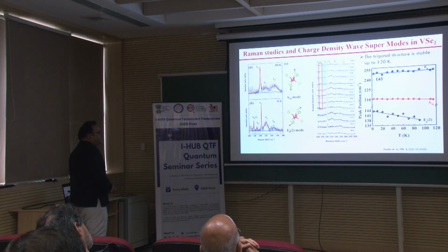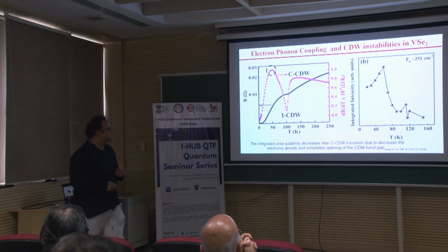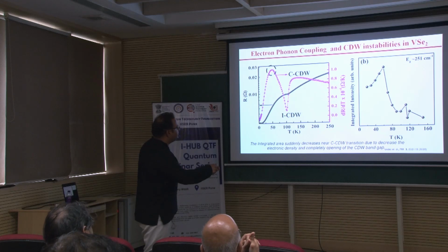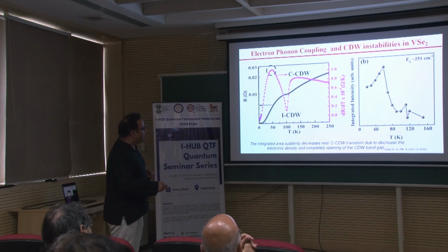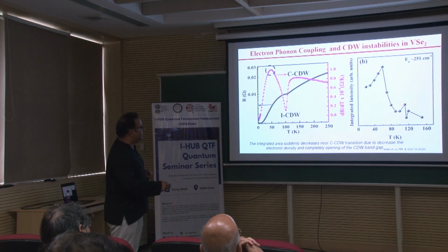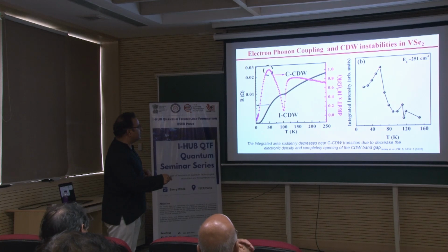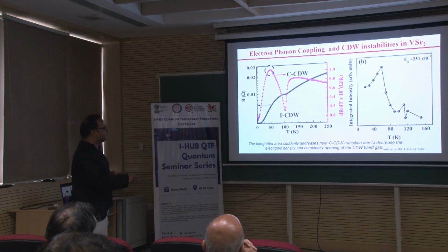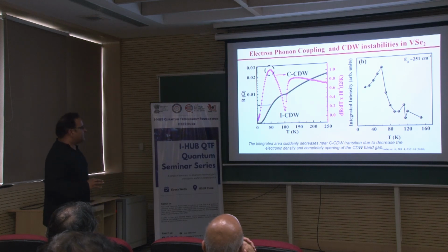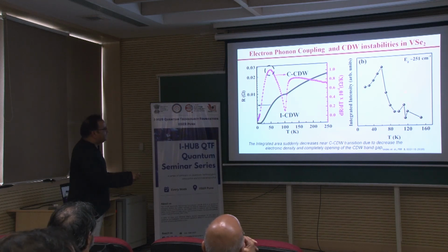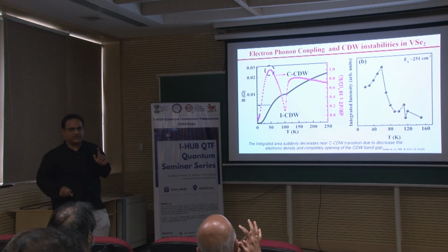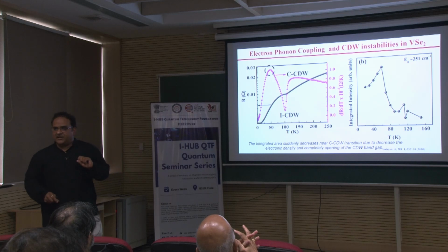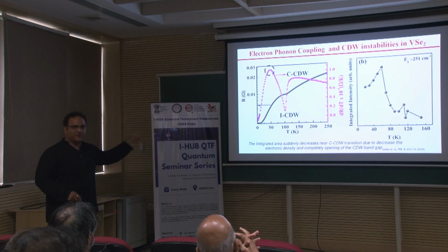This is just the temperature dependence, with the usual softening of the phonons. But what is important here is the integrated intensity of the Raman mode specific to the Eg mode. You go from here to here, from 120 Kelvin to almost 40 Kelvin, and you have instabilities in the structure which are shown in the integrated intensity. When you go further down to low temperature, you again have a hardening. So this represents a new kind of ordering coming up. What we wanted to convey is that these instabilities come from the involvement of electron phonon coupling, and it is not the Fermi surface nesting, it is the electron phonon coupling that is more important in these materials.